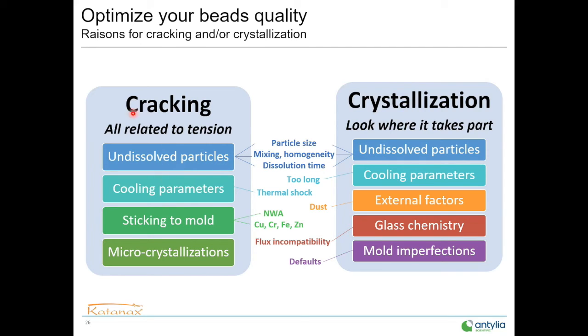If we look for other reasons for cracking, sticking to the mold is something we see relatively often. If it sticks too much, it will create a lot of tension at cooling and can lead to cracking. We talk here about the lack of a non-wetting agent, or a typical element in your sample that can naturally increase the sticking of the fusion mixture. Microcrystallization, sometimes difficult to see with the naked eye, will be a local defect of the glass that can eventually cause cracking. As you can see, all this is related to tension in the beads and eventually leads to cracks.